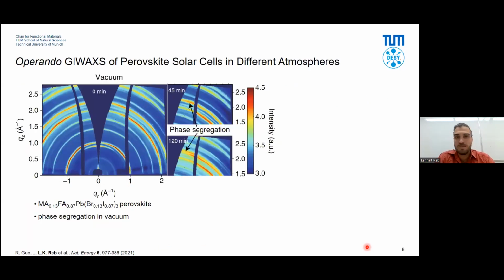In another example, I'm showing you operando GIWAXS of a perovskite solar cell, and in this case, in different atmospheres. So here we have this pattern at the start in vacuum, and we illuminate the sample in vacuum, and we operate the solar cell at the same time. And what we can see, so this is the first order perovskite, as you've seen before. Let's go to the second order, because there we have a higher angular resolution.